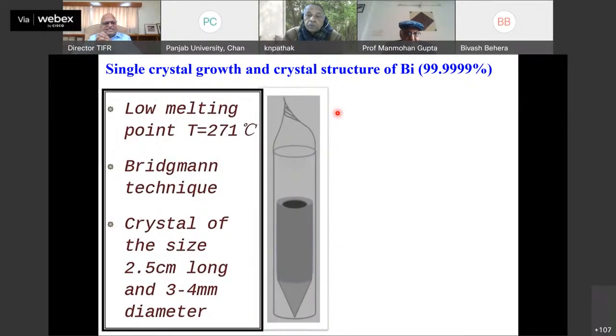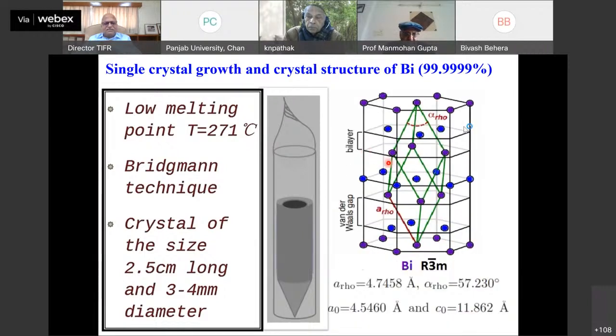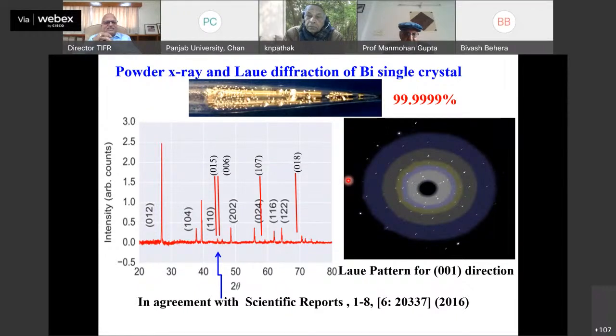And so we decided to grow this bismuth crystal, and that can be grown very easily. Actually, you can do it even in air. Of course, the quality of the bismuth will not be that good, but it grows very nicely. You can grow very large crystals and so on, as we did in the TIFR lab. This is the rhombohedral structure of bismuth. And once we do this, you see that very shiny crystal which comes out, you can align it with single crystal diffraction, and you can measure the transport properties. But before that, you crush the crystal and see whether the X-rays are matching with the standard ones, and also see the Laue pattern of the crystallinity.